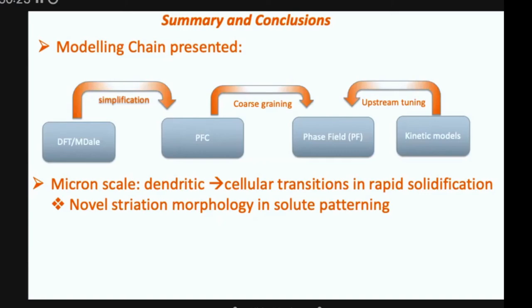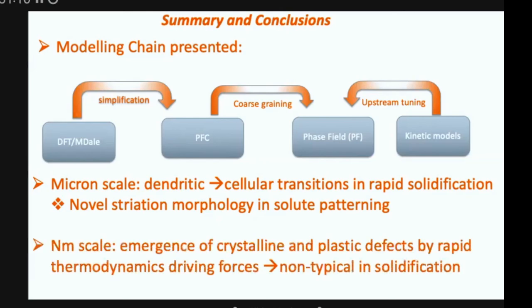People generally, you'll never find a book that talks about crystal plasticity in the same chapter that talks about solidification. Very rare. Usually you say, okay, this is really just chemistry and thermodynamics making patterns, and crystal plasticity is about taking a block of metal and just banging it and bending. But here now we have a case during these rapid processes where certainly in the applications world it's causing a lot of head scratching because you're getting what you think is a solidified crystal full of defects that you didn't think would be there just based on the solidification process itself. And it's the rapidity of the driving force at the interface we think that's spawning these defects that then work their way and quench into the solid and cause the orientation changes.